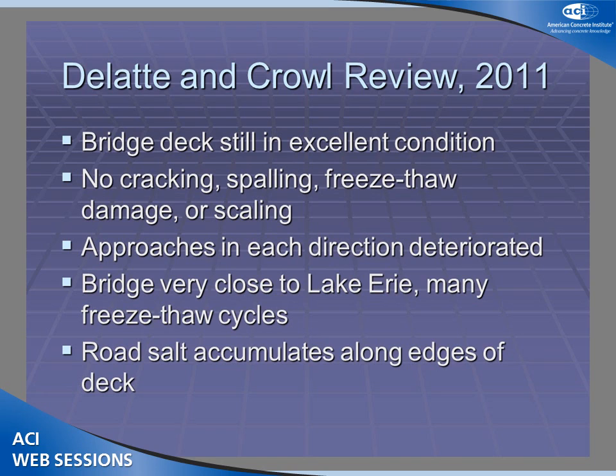What's interesting is you can almost tell where this starts by the deterioration from the approaches, because you go out these approaches, which are conventional concrete. Now they may be older, but they are all chewed up. They have all these problems you'd expect to find in this area. And then you get on the bridge deck and it looks great. And then you get off and you're on the approaches and those don't look so good either.